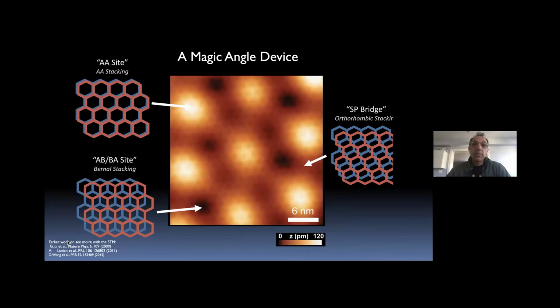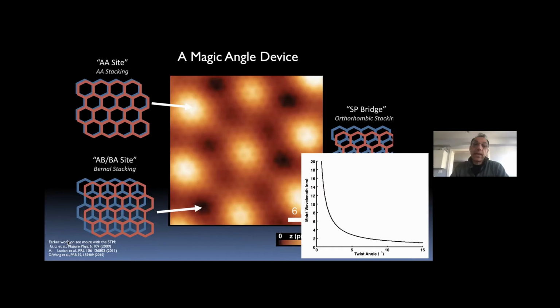So it's taken us a lot of time to make very clean magic angle devices. I'll spare you the details. What you see when you make these devices, as Dimitri pointed out, is that the stacking of the two different graphene layers on top of one another gives you roughly the AA sites, where the A atom in the graphene sublattice sits on top of the A atom on the other graphene sublattice, or you have AB stacking, where the A atom sits on the B sites and the bridge sites in between. From these images, you can immediately tell what the twist angle is, because the periodicity of the Moiré wavelength depends very sensitively at low angles on the twist angle.